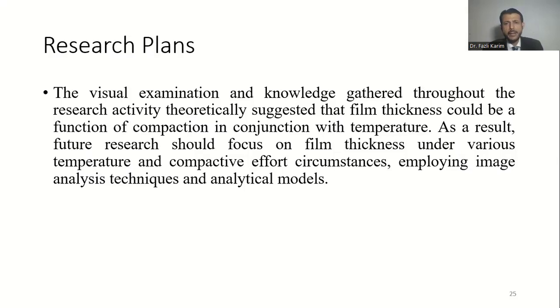Research plans. As already described, the asphalt binder film exists as a non-absorbed binder which fills the approximate distance of 0.5 to 2.4 micrometer. Although in the current study the effect of temperature was measured, the effect of compaction was beyond the target area, because the compactive effort was constant. But the visual examination and knowledge gathered throughout the research theoretically suggested that the film thickness could be a function of compaction in conjunction with temperature. As a result, future research should focus on film thickness under various temperature and compactive effort circumstances, employing image analysis techniques and analytical models.